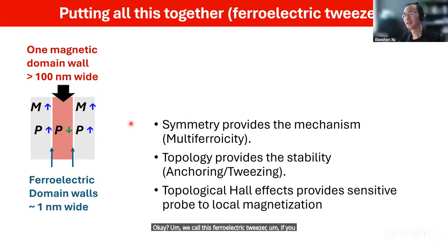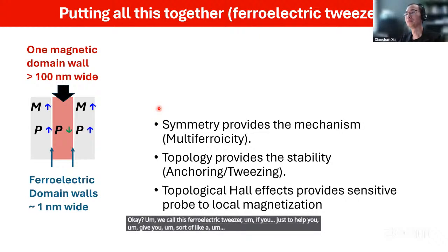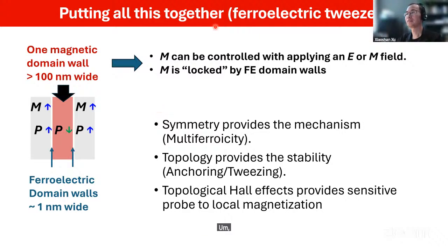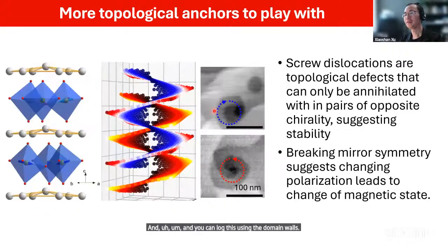Just to give you a visualization in your head, in this case the magnetic property can be controlled by applying an electric field, and you can lock this using the domain walls. And there is actually more to play. This is going a little bit more wild, about topology. For example, as we mentioned, we can make use of the imperfection of the material, something called screw dislocation. So an arrangement of atoms like this, which we see in the experiment, can certainly anchor or pin down certain magnetic states. All right, so I think that's all.